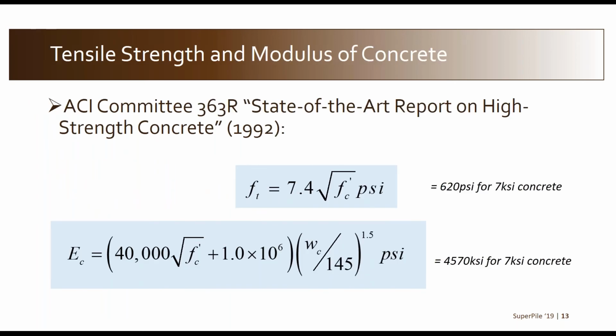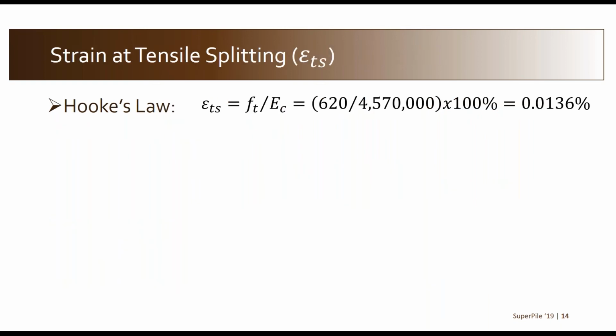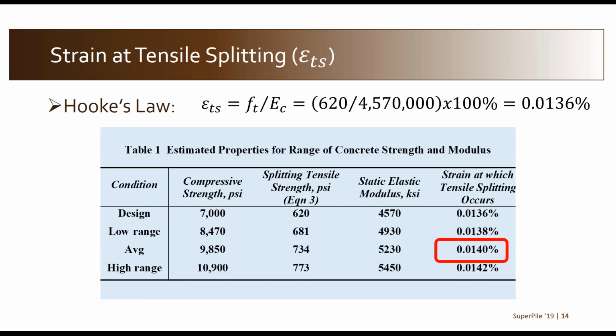This is high-strength concrete because it's a precast pile. The design strength was 7 ksi. So referencing this ACI report on properties for high-strength concrete, we estimated the tensile strength and modulus to be about 620 psi and 4,500 ksi respectively. We can relate stress, strain, and modulus using Hooke's law, and we would estimate that it would take a strain of about 0.014% to cause a tensile splitting failure. And that's confirmed with values reported in that same ACI report that on average, high-strength concrete will rupture in tension when experiencing a strain of about 0.014%.